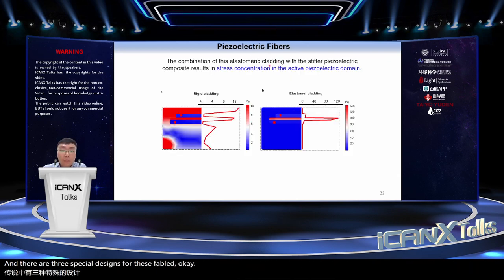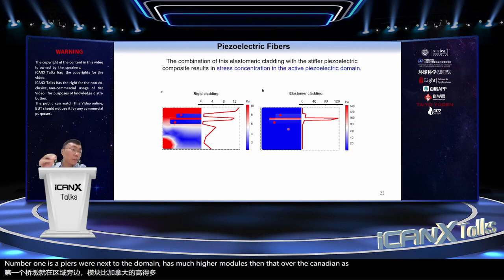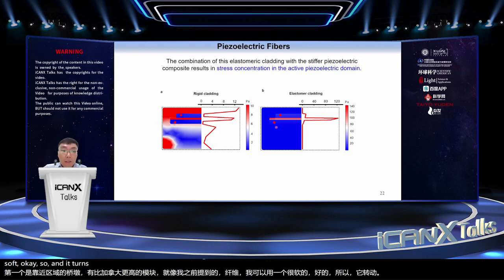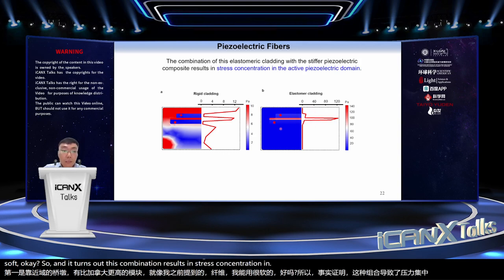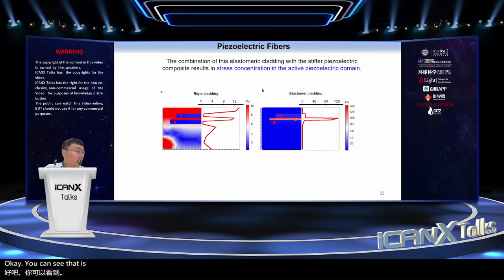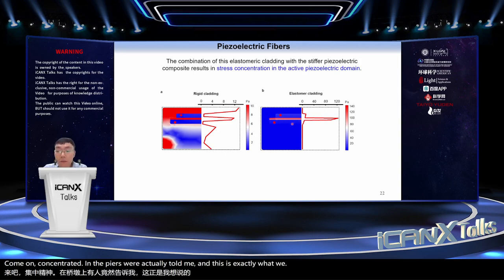The number one is that the piezoelectric domain has a much higher modulus than that of the cladding. As I mentioned before, the fiber cladding is very soft. It turns out this combination results in stress concentration in the piezoelectric domain, as shown by the COMSOL simulation. You can see that the stress is pretty much all concentrated in the piezoelectric domain. And this is exactly what we want, because this enables high efficiency of energy conversion.